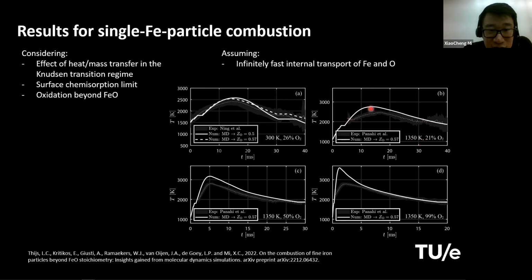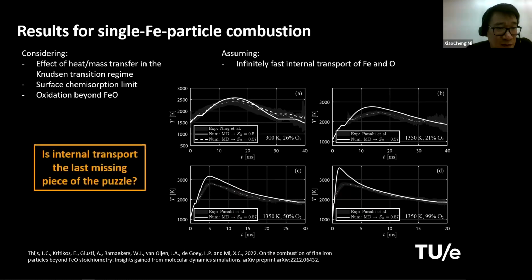It's not too bad, the match, but you can see the peak temperature also somehow overshoot over the experimental result. And this overshoot becomes larger and larger as you go to higher oxygen concentrations. And again, the experimental result doesn't show a very significant peak temperature increase as you go from 50 to 100% oxygen in the gas phase. So this leads us to our final, or I hope it's final, but maybe there are also other unknowns. We were wondering, is this internal transport really the last missing piece of the puzzle, right?